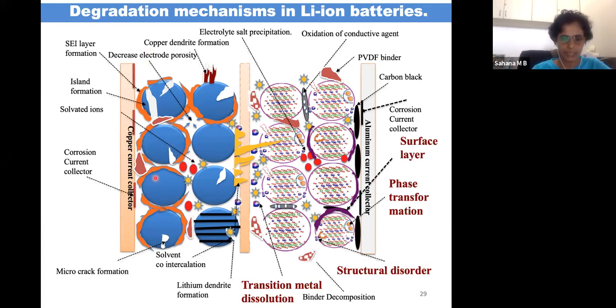Now let's take the left hand side, which is a representation of an anode. These circles correspond to graphite particles, which are made up of layers of graphite. In between, only the lithium ion should go, but there is a possibility that the solvent and the anions like LiPF6 can go in, and the distance between the layers of graphite can increase. In turn, that can spoil the anode material.